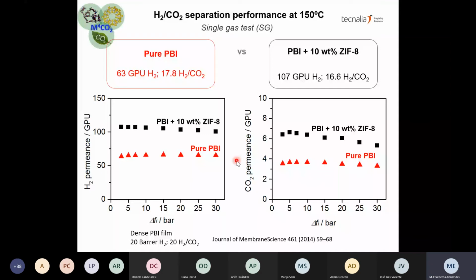The membranes were first tested for single gases at different transmembrane pressure. As you can see in these graphs, by the addition of 10% ZIF-8, we managed to almost double the hydrogen and CO2 permeance. The hydrogen permeance was increased from 63 GPUs up to 107 GPUs by the addition of the MOF. For the pure PBI, hydrogen and CO2 permeance were not influenced by the feed pressure. They kept constant.